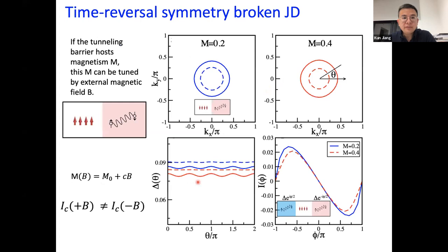The simplest example is assuming the tunnel barrier has some local magnetization that can be tuned by an external magnetic field. If the magnetization is different, the Fermi surface splitting of the metallic barrier region is also very different. The critical current for M=0.2 and M=0.4 are also very different. Then we can achieve critical currents in positive and negative B-fields that are not equal to each other.